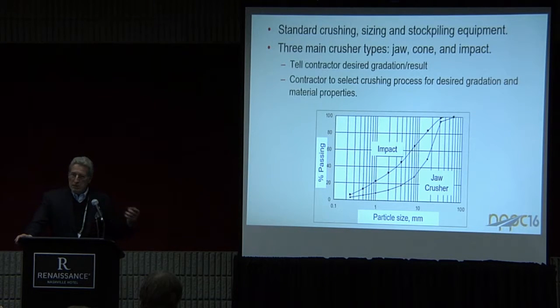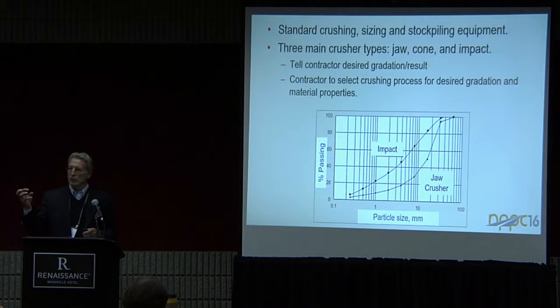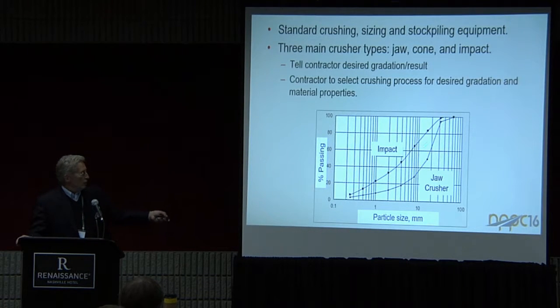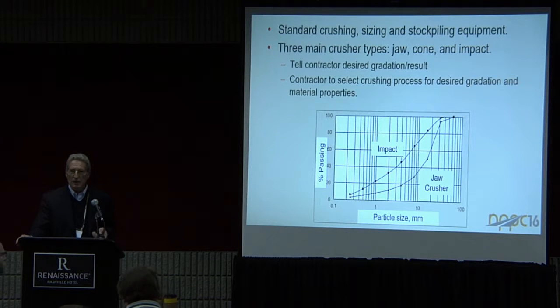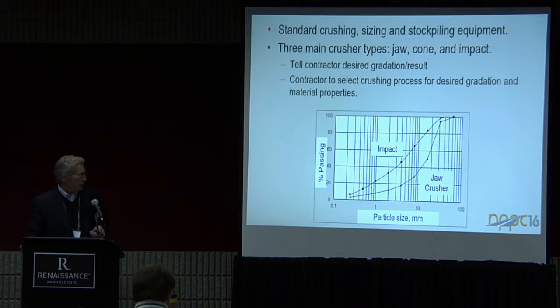You get granite versus limestone versus gravel, those different aggregate types, cement will tend to bond to those different aggregates differently, and you'll get different reclamation efficiencies out of those. And using different crushers on the same aggregate, an impact crusher is going to tend to give you a finer grain distribution. More fines is going to tend to remove a lot more mortar. The jaw crusher is going to tend to give you a coarser particle size distribution. So you'll have a higher reclamation efficiency and fewer fines being produced.